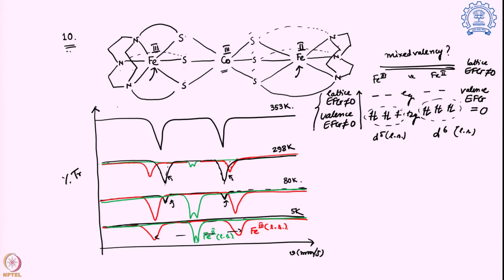So altogether it is going to have a very asymmetric electric field gradient, and that is going to show up over here. That is why iron 3 plus is so widely split, whereas in iron 2 plus only the electric field gradient of the lattice comes into play; the valence is shut down. So that is why it is split by only a very small amount, and that is what we are seeing. So now we know exactly what iron 3 plus and iron 2 plus look like. What is the original splitting that we are seeing? What does it represent? We found that it is somewhere in between them, so it is iron 2.5 plus.